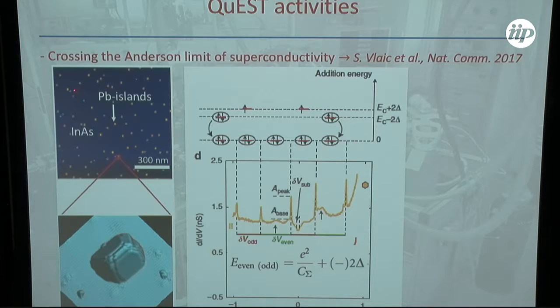We deposited small nanocrystals of lead on the surface of indium arsenide, and in this situation there is a band depletion due to the presence of lead. So lead electronically is floating above indium arsenide. When you put a tunneling tip, you have a double tunneling junction, and you can charge your small islands with electrons.